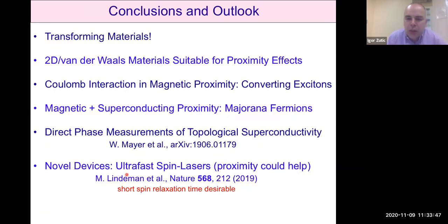So what I was trying to argue is that many decades following first demonstration of proximity effects, we are now in a position to view them more broadly, not just as a curiosity limited to few structures, but as a systematic tool to transform large class of materials, especially if we consider two-dimensional materials and van der Waals heterostructures, then these proximity effects may play a very important role. We may need to include Coulomb interaction in magnetic proximity effects, especially in these transition metal dichalcogenides or other materials where there is a weak screening. Role of excitons is important, and single particle picture is clearly not enough.